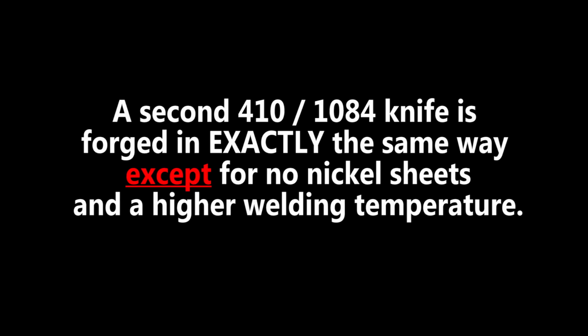So to clarify, that wasn't the core splitting from the quench. That was a bad weld. I don't think it ever welded correctly because we didn't get the forge hot enough. So again, repeated this all with the same construction, same canister, just no nickel sheets and much hotter. The canister was sparking off during the soaks.